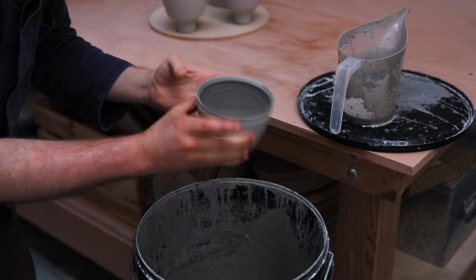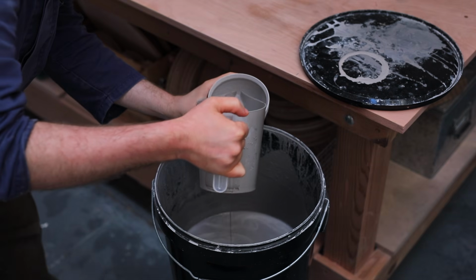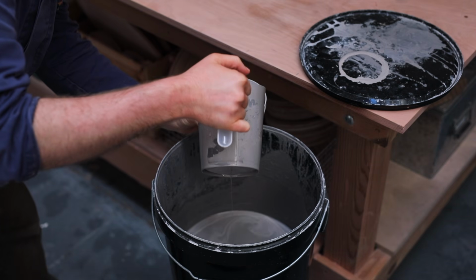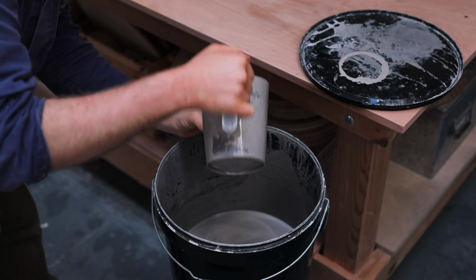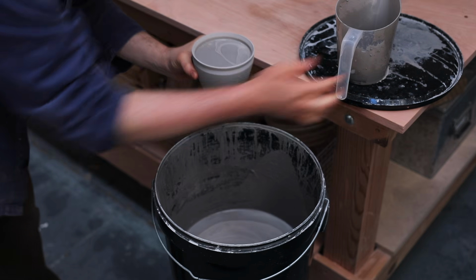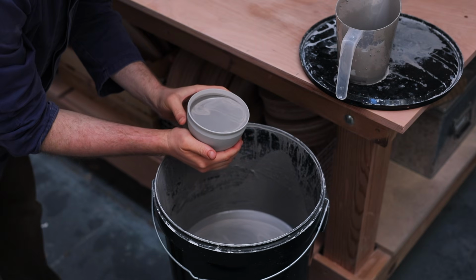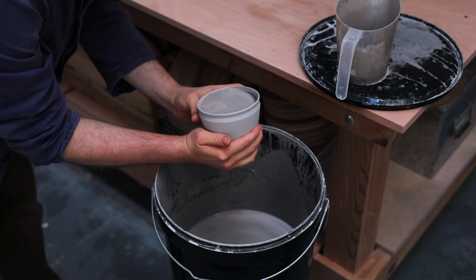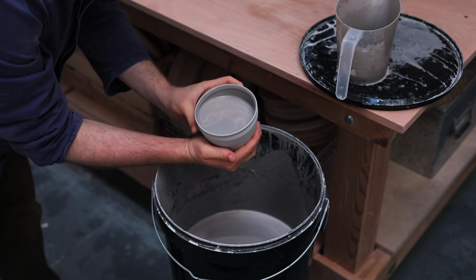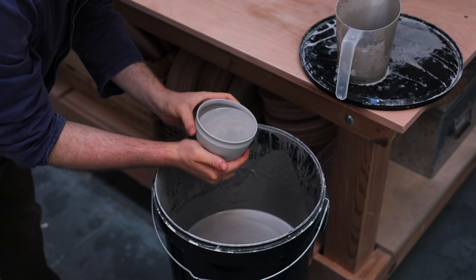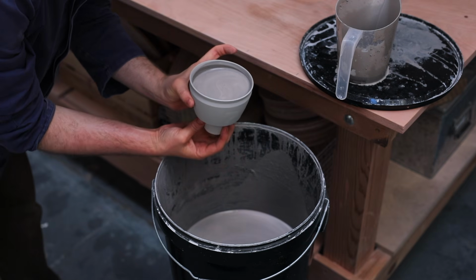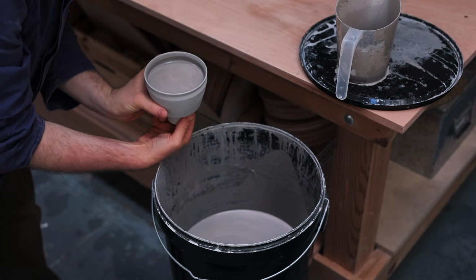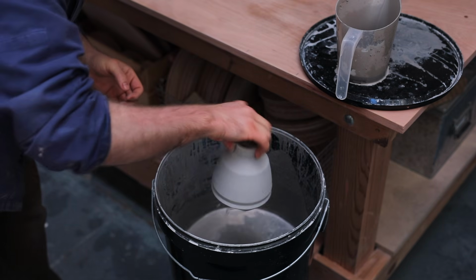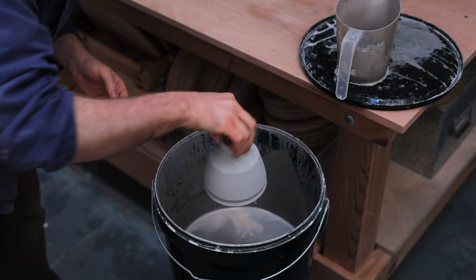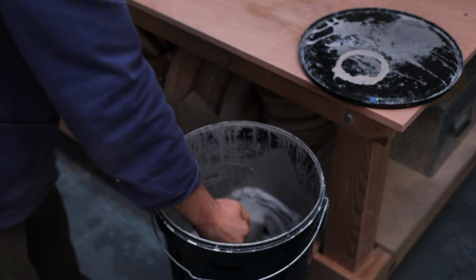Now, what I should have done is held these pots upside down until the glaze had completely dried, as this way drips and slightly thicker surfaces of glaze wouldn't have settled on the interior surface, which, even though I did ultimately get rid of them, scraping them back carefully, they still showed in the finished fired glaze, which is another reason why I think I'm going to ditch this glaze until I've got a spray booth at least, as by applying it that way with a spray gun, I should be able to achieve a really smooth, flush finish across the entire piece.